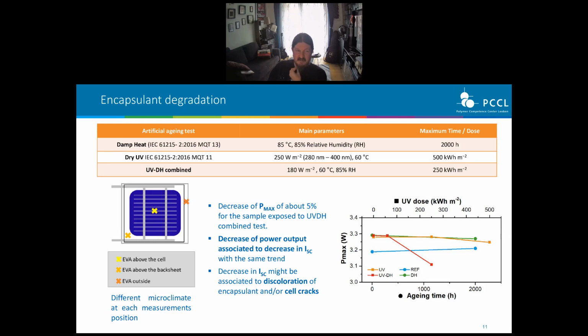This is a study we did on mini modules, where we exposed these modules to 3 different lab tests: a damp heat test for 2000 hours, a dry UV test with a maximum UV dosage of 500 kilowatt hours, and then a combined UV damp heat test up to 250 kilowatt hours of UV dosage. Then we dismantled the modules and analyzed the encapsulant at 3 different positions. First, right in front of the cell, second, right above the backsheet, and third, we took some material that was squeezed out during module lamination, so that was outside the glass, directly exposed to the stresses.